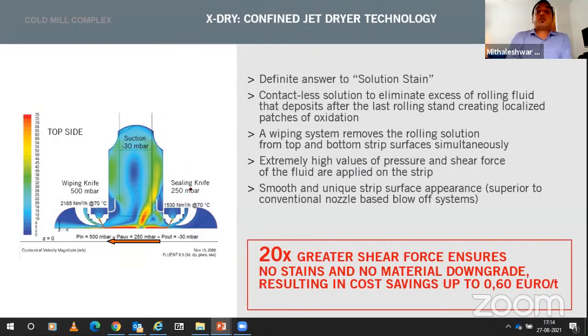If you look at the pressures, the sealing and the wiping we are doing at 250 millibar and 500 millibar, and the suction at -30 millibar. This results in removing everything from the strip, and because of this technology we get about 20 times greater shear force on the strip surface, which ensures no stain and no material downgrade. And if you go to the economical result, we are able to offer our customer 0.6 euro per ton saving on the operating cost.